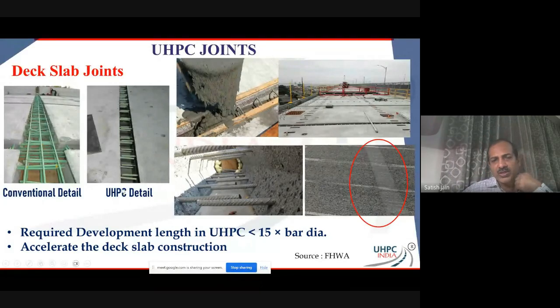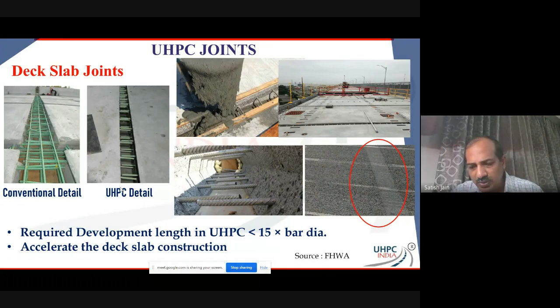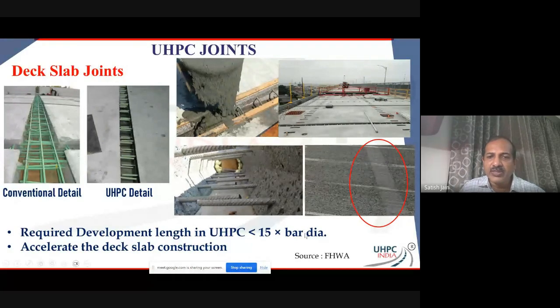And the UHPC joints are sleeker just because of the robust characteristics of the material. To give you a general example, your bond strength between concrete and rebar, you need close to 40 to 50 times the diameter of rebar to develop your rebar. In UHPC, you just need 15 times the bar diameter. That's how good the bond strength is. And so you get sleeker joints.